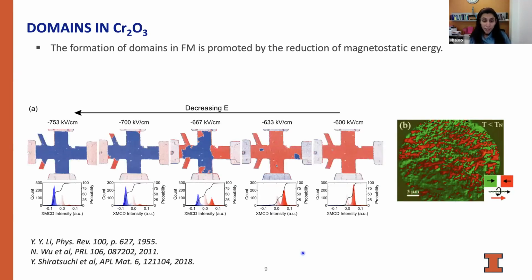And experiments in the magnetoelectric reversal have also shown coercivity that is about 10 to 100 times lower than the magnetic anisotropy. And the switching time that I showed earlier, for the same sample, is on the order of 100 nanoseconds to microseconds, which is very slow. So these results are strongly suggesting that the domain reversal is actually inhomogeneous in nature, and it's not coherent rotation.